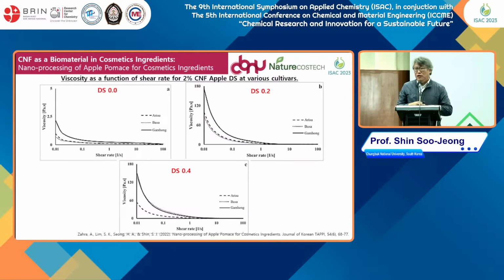Also, in cosmetics we use rheology modifiers to control the drying touch. Most often, carbomers are used as the rheology modifier, so we checked their viscous properties. Without chemical treatment, they have very low viscosity. As we increase carboxymethylation, they improve viscosity, but after DS.2 reaches maximum viscosity, at DS.4 the viscosity starts to decrease.